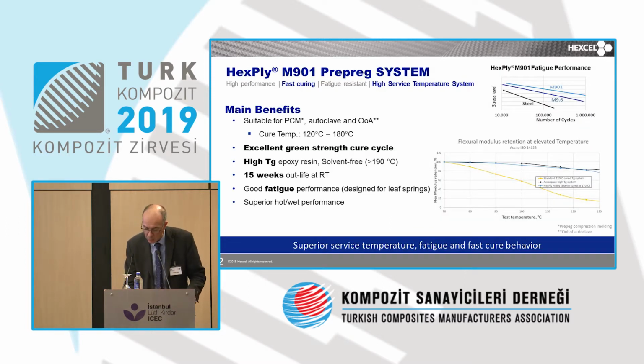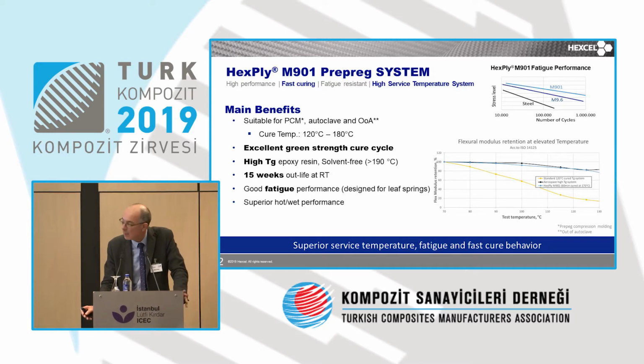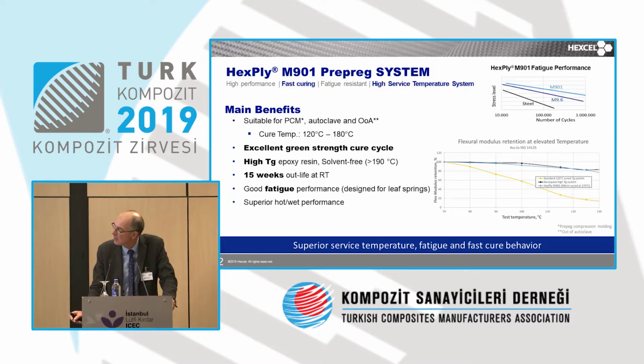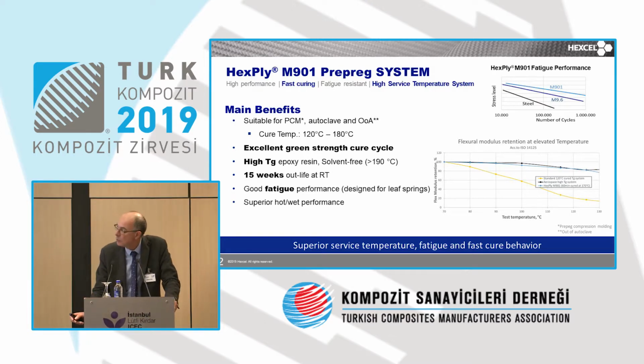The next one is the M901. The M901 is a really fast curing material, fatigue resistant, and a high service temperature system. This really makes it suitable for pressure curing, autoclave, out of autoclave, with cure temperature between 120 and 180. What also makes it different is that the high TG, superior to 190 degrees Celsius, doesn't make it so sensitive to being left at room temperature. It has a 15 weeks proven outlife at room temperature, which really makes it quite interesting if you don't necessarily have all the freezer activity.